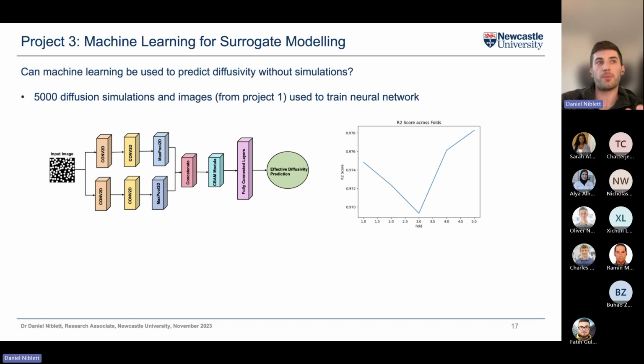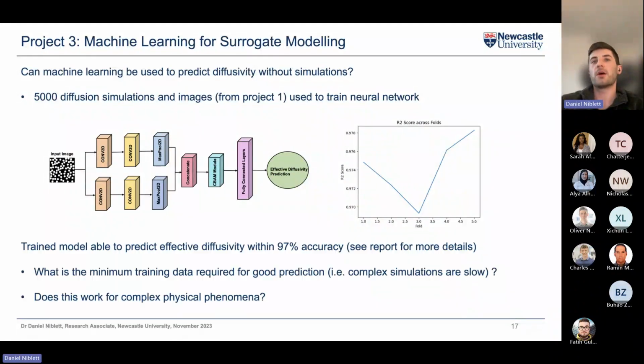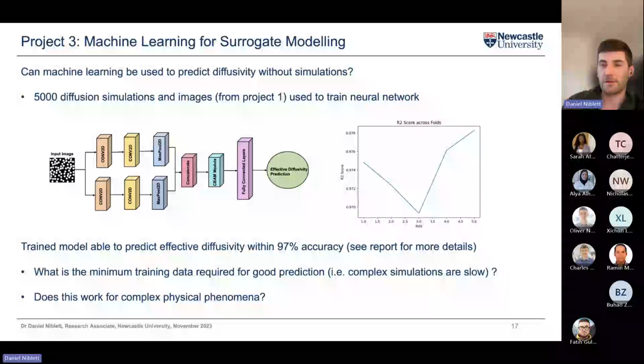And then Kiyotana built a neural network which could take the input image, so just the raw binary image of the microstructure, and then through the neural network be able to predict the effective diffusivity without a simulation. And with that, we were able to get within a 97% accuracy, with more details in the full report if you're interested.